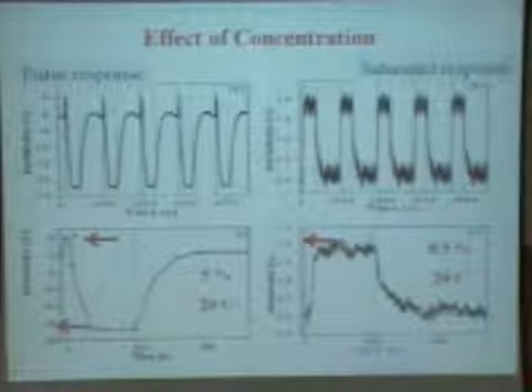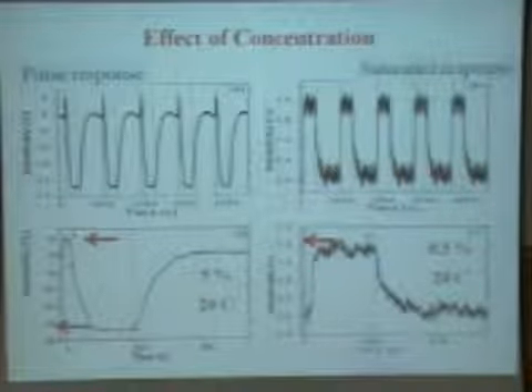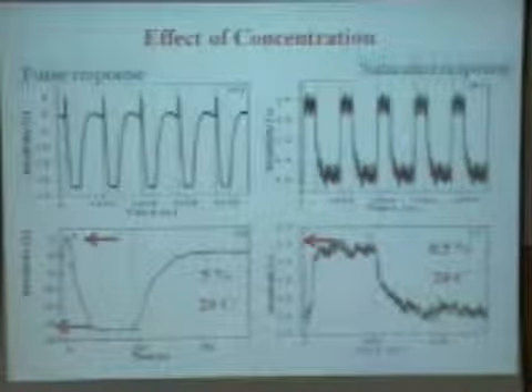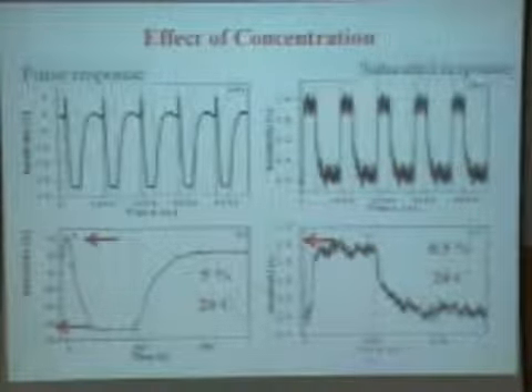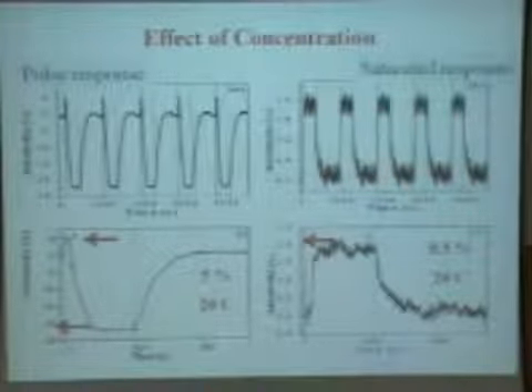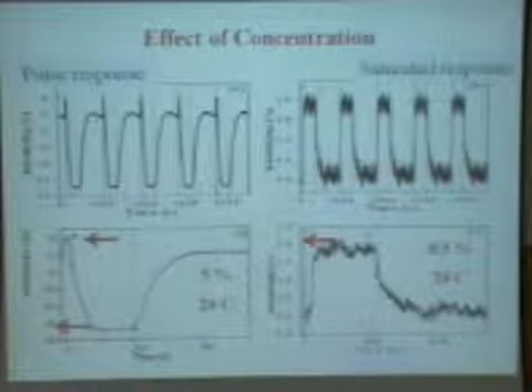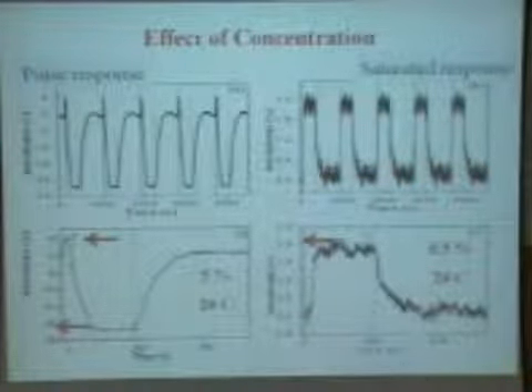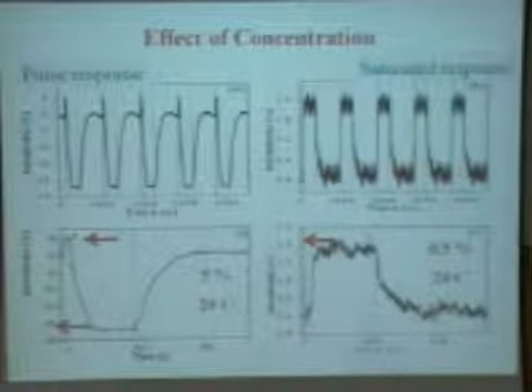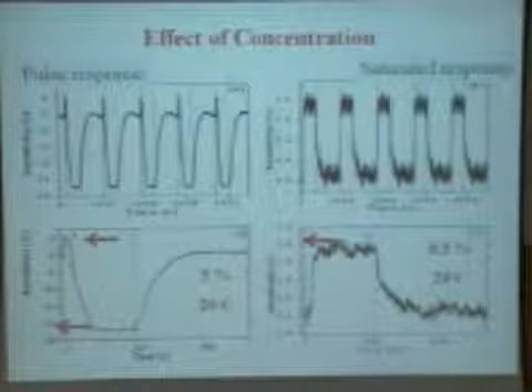What we observe now is that the pulse-like response which I was mentioning and the saturated response is a function of hydrogen concentration, a function of the measurement temperature, and a function of the nanoparticle size. In fact, there are a large number of processes taking place when the hydrogen is interacting with the palladium. What we are observing is a simple increase in the resistance, but that increase is taking place because of 2 or 3 physical processes.